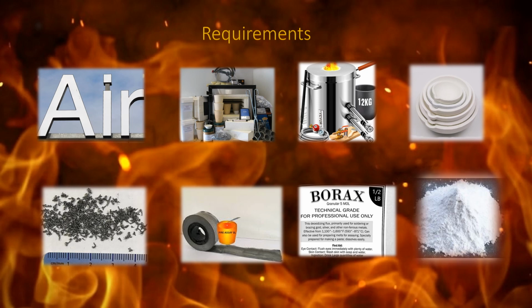The silica would normally not be required, however. If the sample does not contain silica, then a small amount will be added. It is used to slag off any excess lead oxide, as lead oxide will attack the scorifying dish.